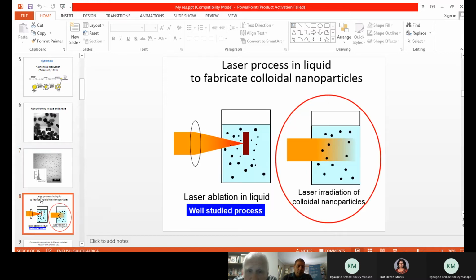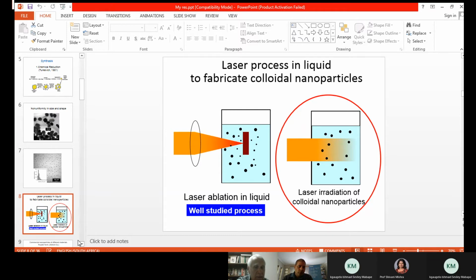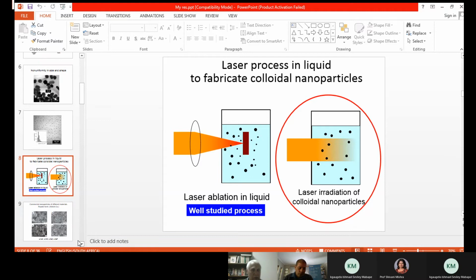Let's move to the next slide. So I stopped on this. As I already told you, the literature widely discusses the first process, laser ablation in liquid. In this process, we concentrate the laser beam in one point and put this point on the surface of a solid immersed in liquid. In the case of silver nanoparticles, we put a silver plate in water with citrate. When we ablate it, we produce nanoparticles.